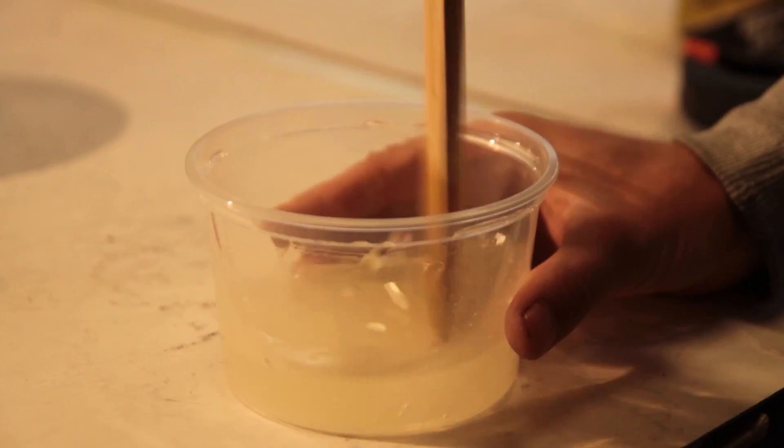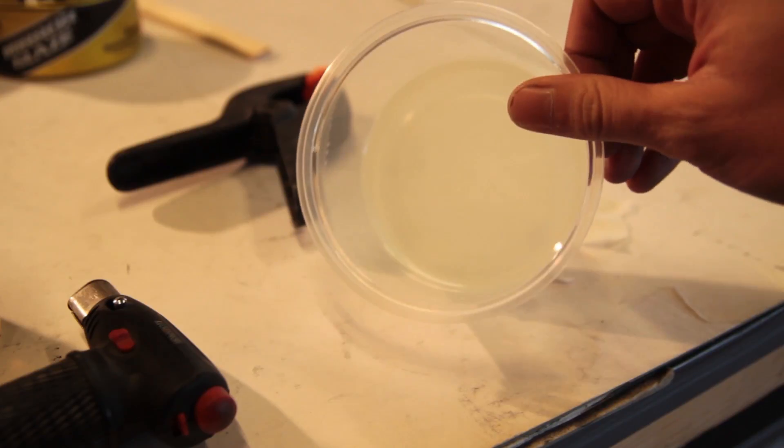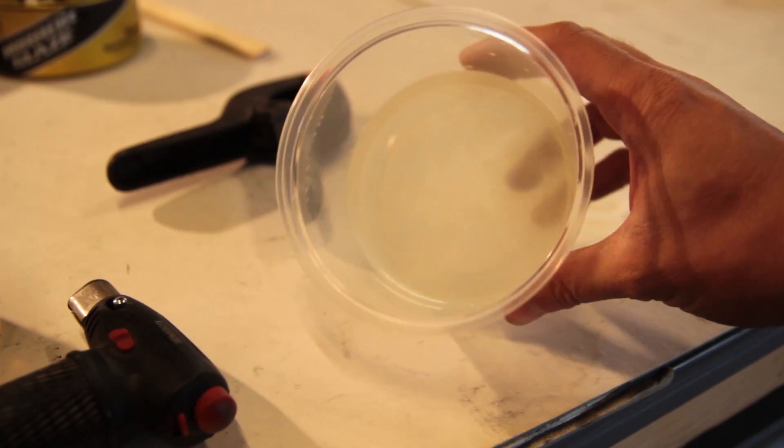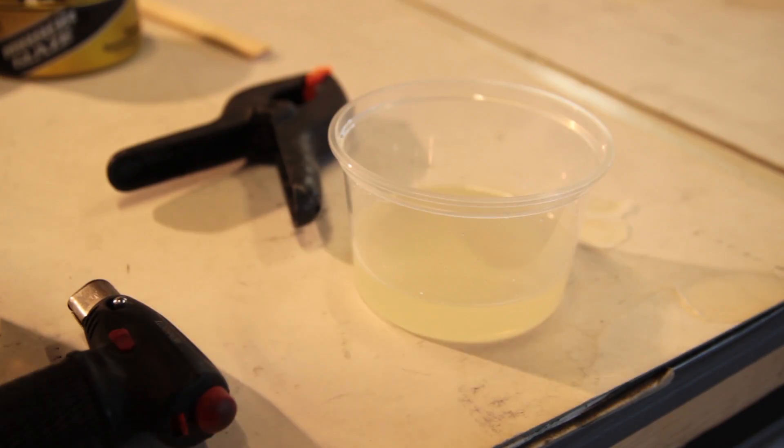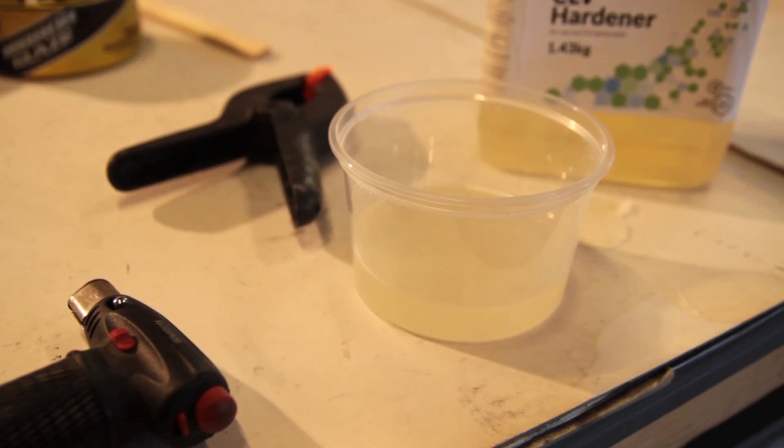And just keep in mind that this resin was from 2016. So it's already two, almost two and a half years later, and the resin is still okay. But I would always advise you to do a test run with around 100 grams in a cup, just to see if the exothermal reaction is still okay or not.